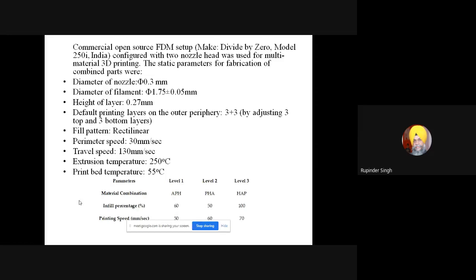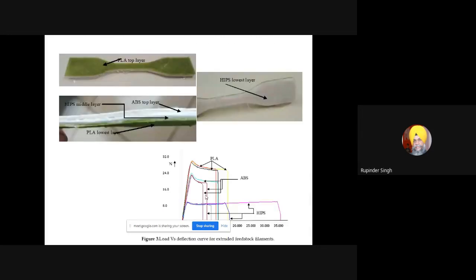Here, for some of the experiments we put the ABS on the top, for some of the parameters we put the PLA on the top, and for some we put the HIPS on the top, and we followed some DOE. It may be Taguchi, RSM, any DOE you can think of, and then you try to see what the effect is. Now you see here are some of the tensile coupons that we printed with different phases, like in this case PLA on the top, then ABS on the top, then HIPS on the top, like that.